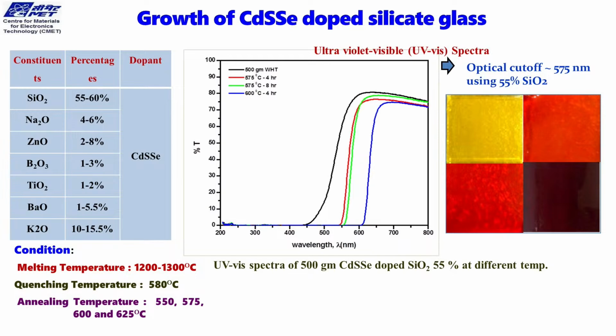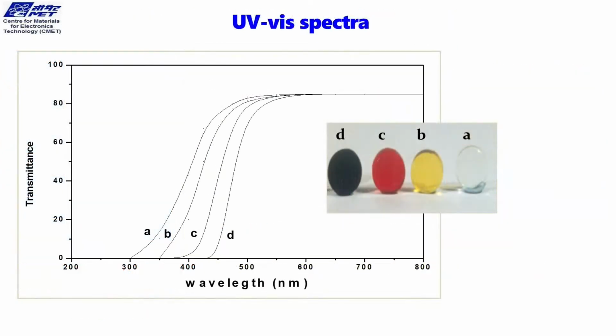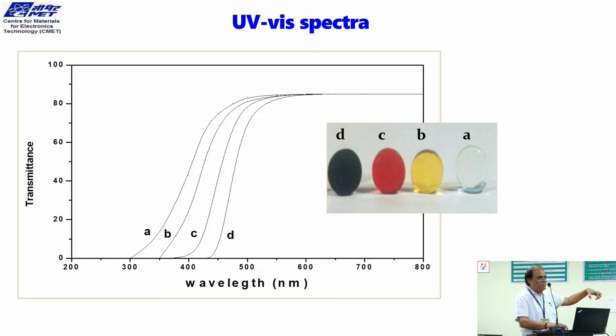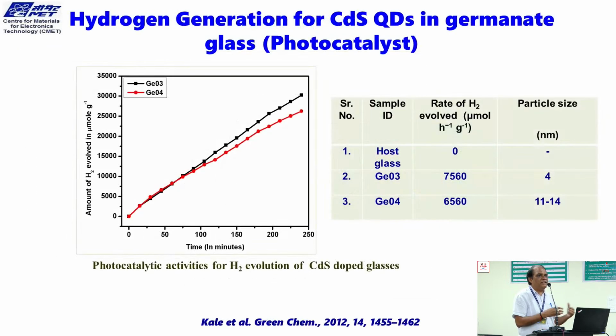So we have to catch this kind of properties for hydrogen evolution. And you can see initially it is transparent, then as you grow cadmium sulfide or any other particles in it, there is a change in the properties. This is the hydrogen generation we did with this glass, and we found that it is much better as compared to other powders. You can see the very linear hydrogen production we can observe.